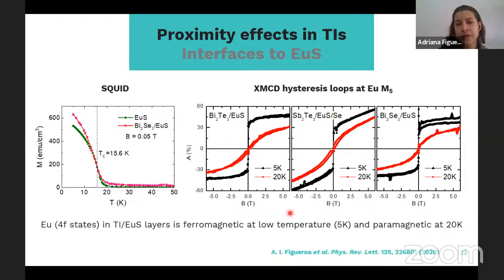In terms of the magnetic order temperature, when we measured them with SQUID, we don't see any difference between the single layer europium sulfide as compared with one europium sulfide interface with the TI. So we find the same Curie temperature around 15 Kelvin or so. And that is also observed with the XMCD measurements, because we see that these layers are ferromagnetic at low temperatures and paramagnetic at 20 Kelvin.